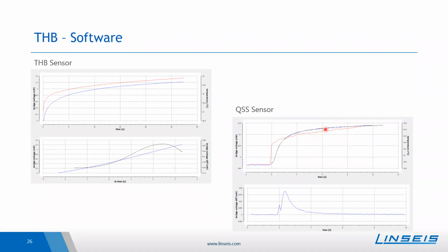For the QSS sensor, we also detect temperature increase and the bridge voltage. On the bottom, one also sees then the derivative of it. The most important curve here is the upper blue one, so the bridge voltage, which is measured. One can see here that we are in the clear transient state, so the temperature is changing, and in the later times we approach a more or less steady state, so a more or less straight horizontal line is approached. From the measurement times, you can also see that the time is very short. Here with the THB sensor, PMMA was measured with a measurement time below 30 seconds. And with the QSS sensor, a titanium sample was measured with a measurement time of about 10 seconds. So, as already mentioned, the measurement time is very low.